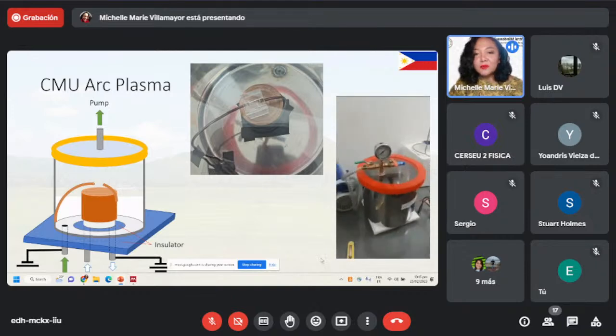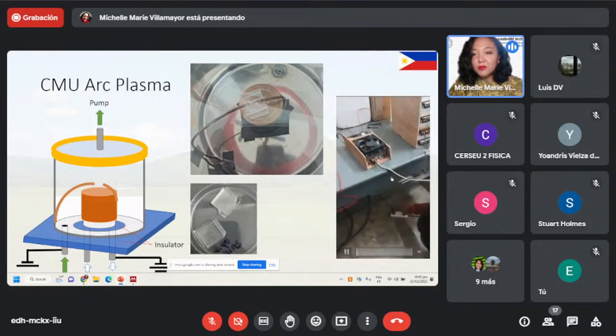So they were celebrating because it was the first time that the discharge was controlled to more than a minute. Previously, when we ignited the plasma, the power supply would start to smoke, and that won't work anymore after the second experiment. But this one was a repeatable experiment, and it was possible to ignite the plasma. So now it was time to check if there's a copper deposit, because ideally we would like to have copper deposited on our acrylic substrate.